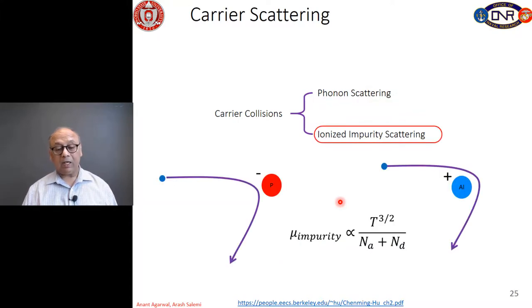So that's shown here. And for the other type of scattering, which is the impurity scattering we described to you, we find that as we raise the temperature, the probability of scattering actually reduces, and therefore the mobility improves as we increase the temperature, and the dependence is T to the power of 3/2. And again, impurity scattering is inversely proportional to total number of impurity atoms. A material could contain both P-type and N-type materials, and therefore we use the sum of the N-type and P-type impurities, Na plus Nd. So higher doped materials will have lower mobility, but the mobility will increase with temperature.